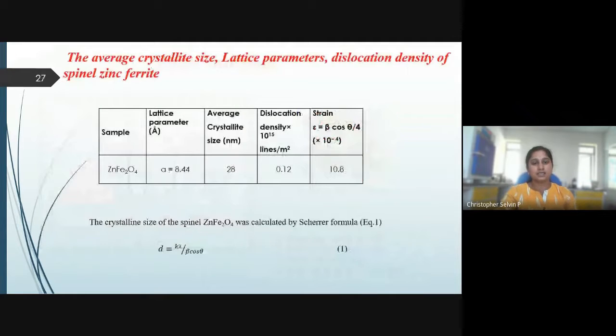These are the other structural parameters obtained out of XRD results. By means of the Debye-Scherrer formula, we can calculate the crystallite size, which is in the range of 28 nanometer. And dislocation density is also very low, which indicates low defect concentration in this material, which is 0.12 into 10 power 15. Whereas the strain is also very low, which is 1 into 10 power minus 3.